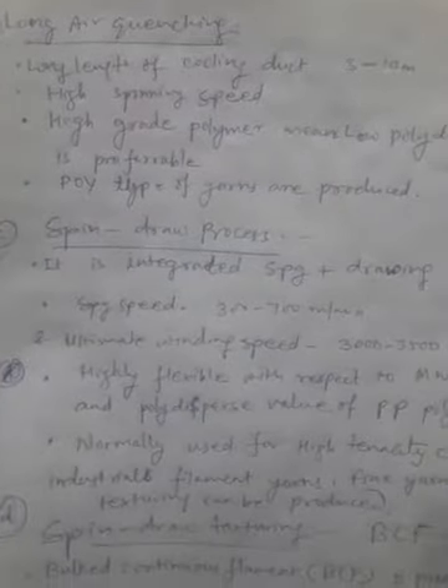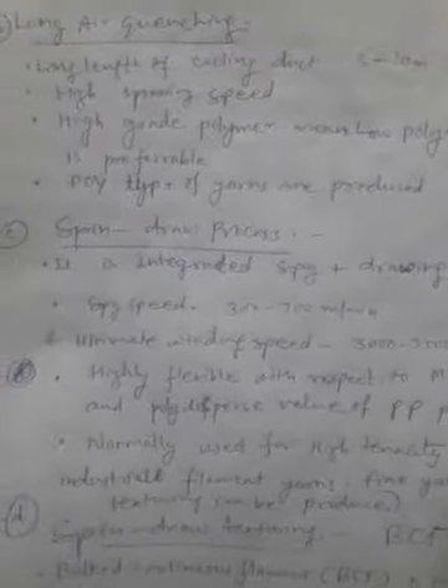Another important spinning method is the long air quenching method. Here the cooling duct is 3 to 10 meters long. High spinning speed can be kept in this one, and high grade polymer is a prerequisite for the spinning. That means a low polydispersity value is preferable and high molecular weight is preferable.